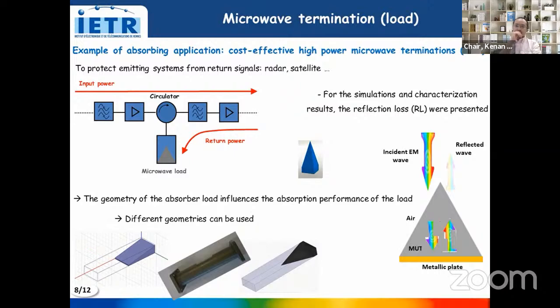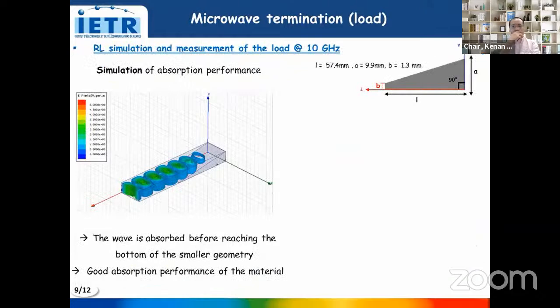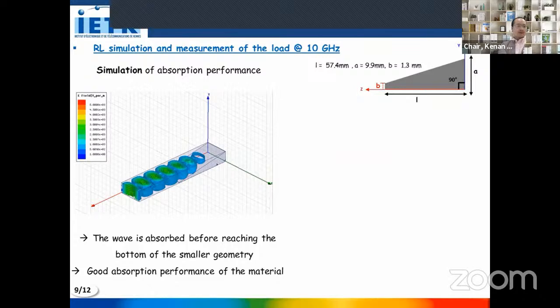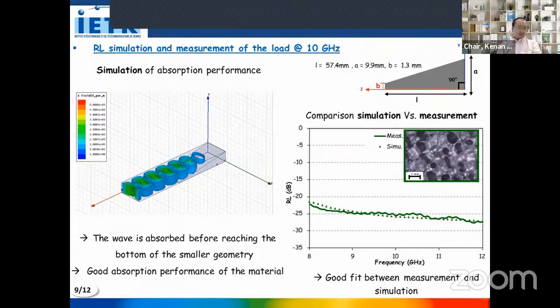Here I show an example of application of these absorbers. It consists of a cost-effective high-power microwave termination to protect emitting systems from return signals. The simulation of absorption performance of this load shows that the wave is absorbed before reaching the bottom of the geometry, which confirms the good absorption performance of our material. Moreover, a good fit is obtained between simulation and measurement of the reflection loss of this absorber.